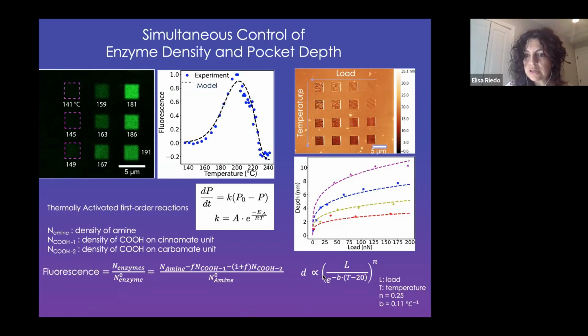So this equation is essentially giving us the fitting for the experimental curves, and together with this equation, which is similar to what we have before, but now we also have to keep in mind that there is a passivation going on, so the activation of negatively and positively charged molecules, and that's why here the fluorescence has a maximum. So in the beginning you expose only the positive charges, so the enzyme won't attach. But then at high temperature you start to expose also the negative charges, which repel the enzyme. So you have a maximum and then a decrease.